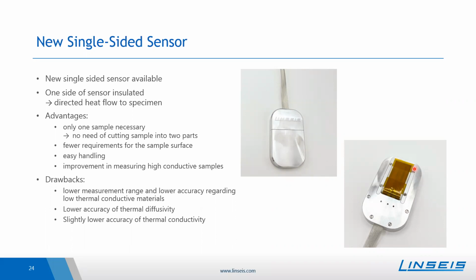As always, if there are some advantages, there are also some disadvantages. The disadvantages of this single-sided sensor are that the measurement of low conductive materials, especially insulating materials, is not so easy, or even not possible, and shows a higher uncertainty. Furthermore, if one is interested in the thermal diffusivity, it will also not be possible, or not as good as with the classical two-sample setup.